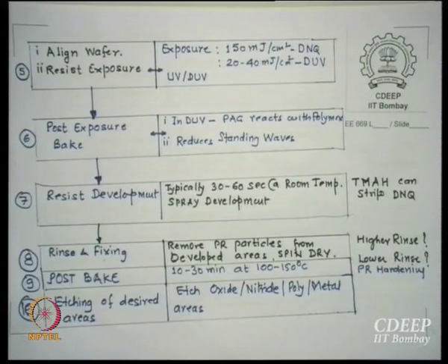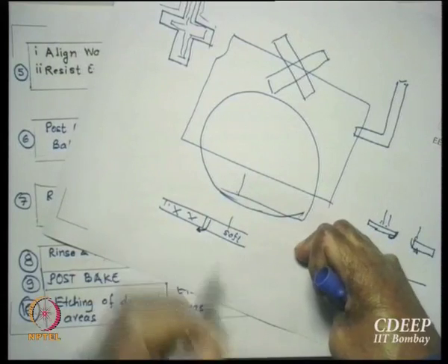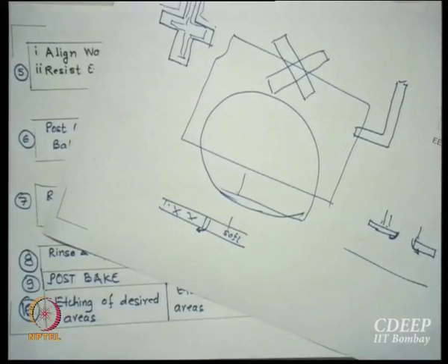What do you mean by resist to develop? The soft portions of the resist are dissolved, okay, and the hard portion is not attacked. So here again, if I do it too long, what can happen? I'll just show you, I'll come back to it. This is my resist area which is hard, okay. This is my soft. So this was getting etched or developed, but part of the developer can get inside and actually lift the hardened resist, okay.